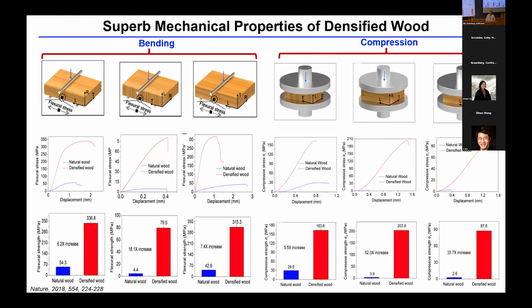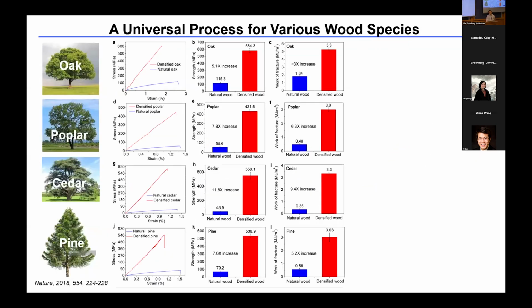So these are the property tests in different directions, and they are related to different applications: how to bend it, a bending test, compression in all 3 directions. And so they are more than the increase of the density, right? So the density of this wood is increased by 3 to 4 times. So if we don't get anything extra from the hydrogen bonding, we should get a 4x performance increase, but we're getting more than 4 in many directions. So we are increasing the interactions between the fibers. It's not merely a simple geometrical effect.